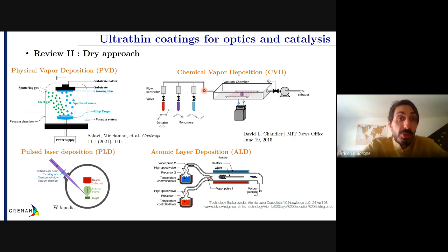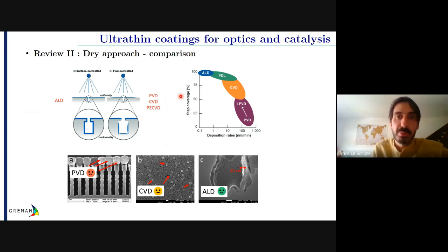Okay. You also can use a dry approach, which is closer to the industry, closer to what we are doing in Tours and what many of you working in clean room facilities do, for instance. So you have PVD, CVD, PLD, and ALD. I don't know if you are familiar with all of them, but I'm not going to comment on this. But of course, I'm going right now to the comparison: ALD allows more conformal deposition when you have cavities, right? Porous silicon is also cavities, or porous materials. And it's much more difficult to have conformality when you use PVD, CVD, or PECVD, for instance, with plasma. So I think for porous semiconductors, you can prefer ALD if you want dry deposition.